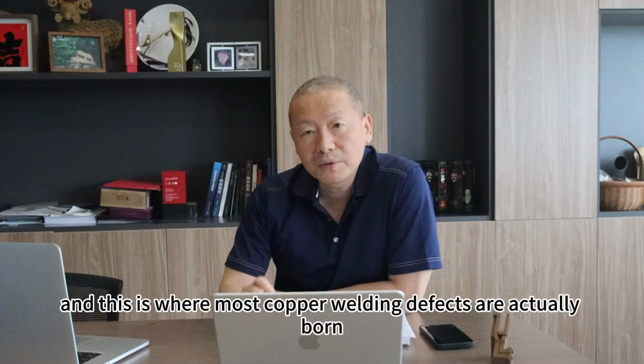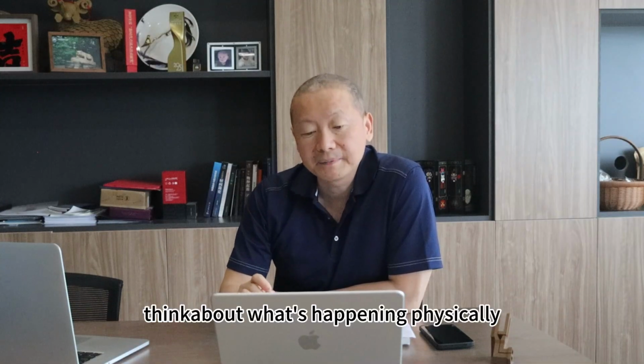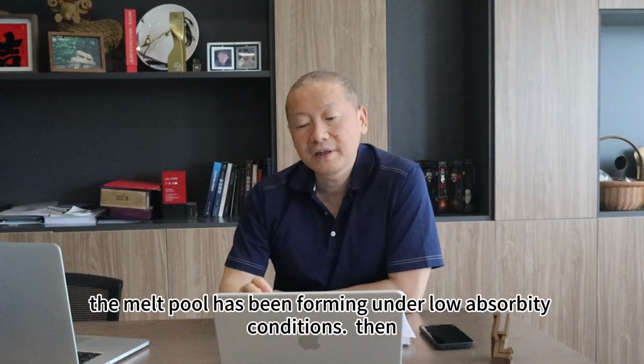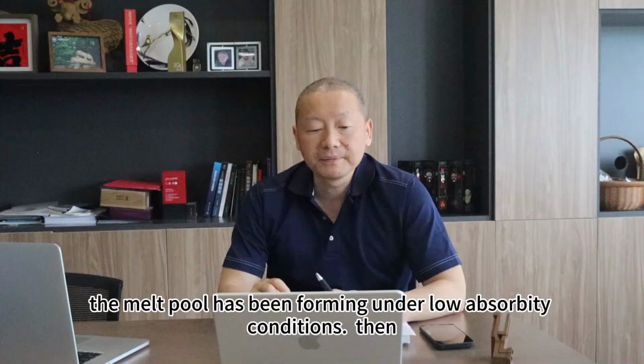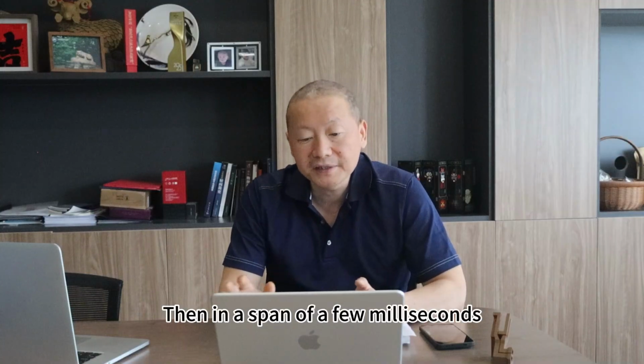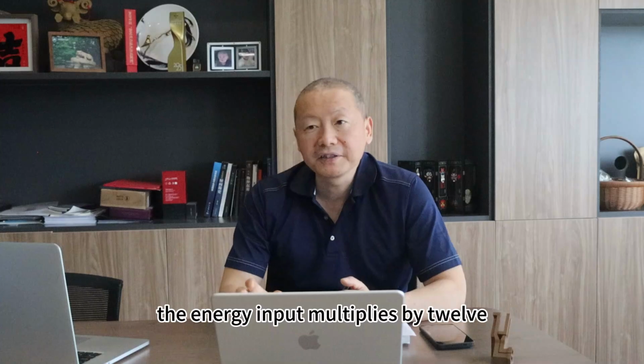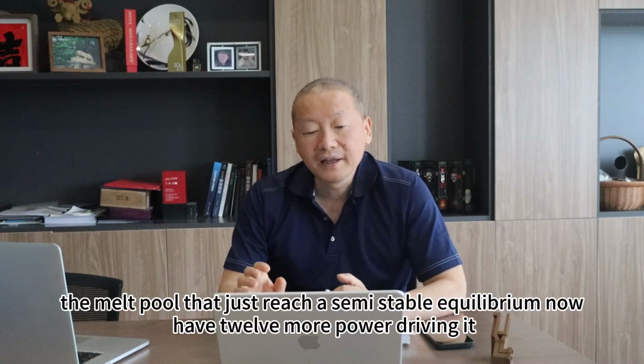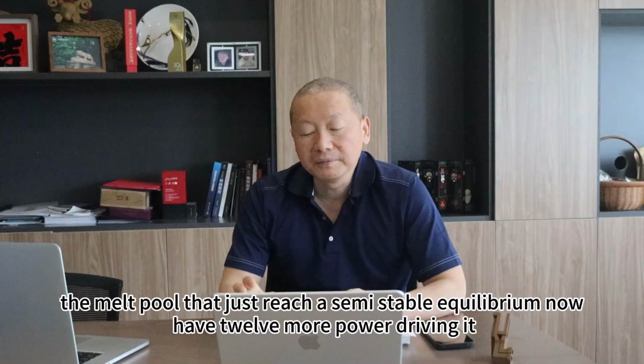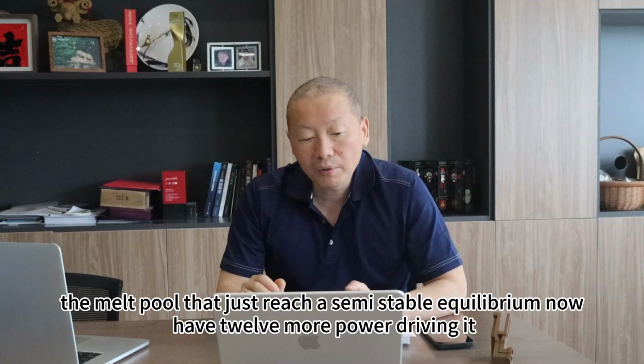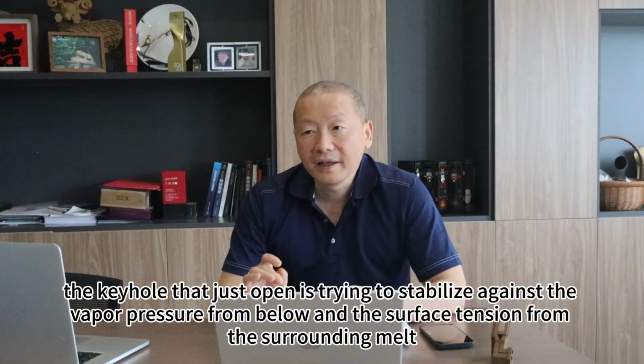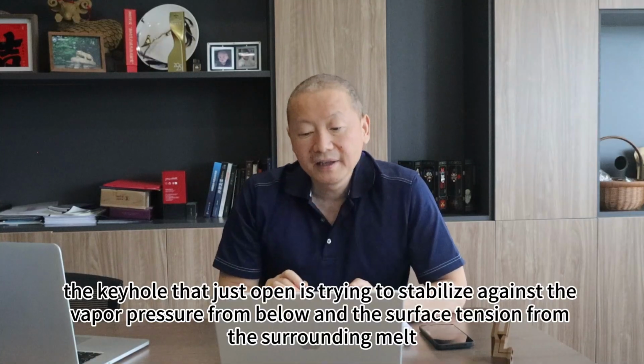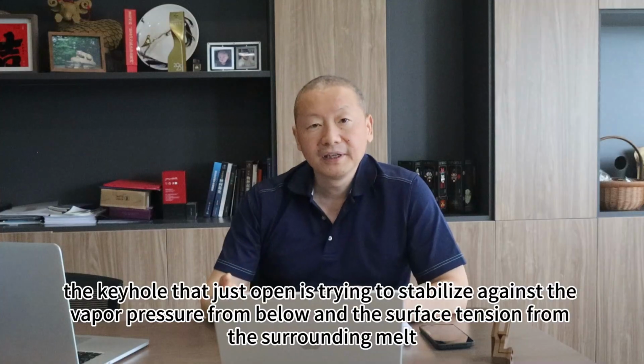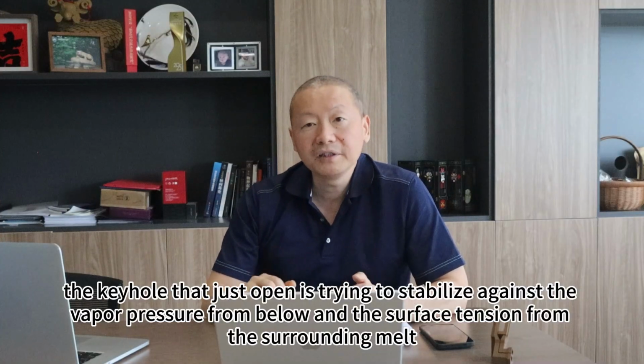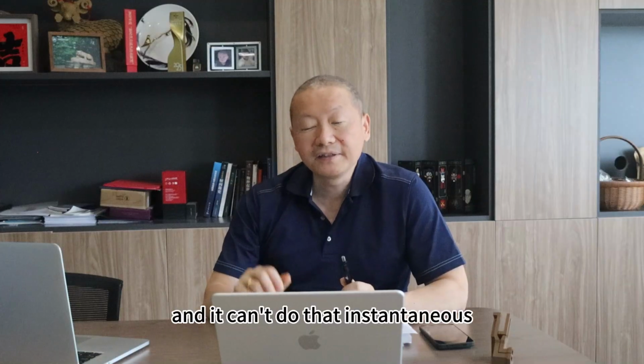And this is where most copper welding defects are actually born. Think about what's happening physically. The melt pool has been forming under low absorptivity conditions. Then, in a span of a few milliseconds, the energy input multiplies by 12. The melt pool that just reached a semi-stable equilibrium now has 12 times more power driving it. The keyhole that just opened is trying to stabilize against the vapor pressure from below and the surface tension from the surrounding melt, and it can't do that instantaneously.